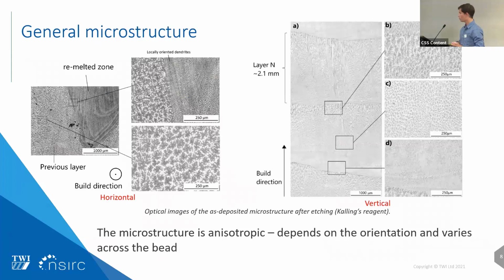So a bit about the microstructure, which is important when we look at the corrosion properties of a material. Here you can see the microstructure of an as-deposited sample. On the left-hand side is the microstructure for a horizontal sample, taken perpendicular to the build direction. On the right-hand side, the same sample taken on the vertical orientation, parallel to the build direction.